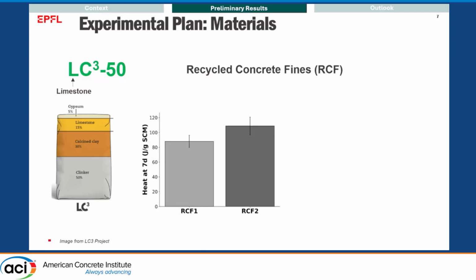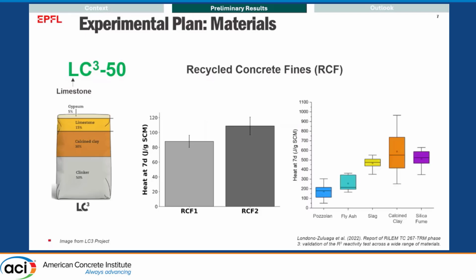So the recycled concrete fines that I was using had an individual R3 heat of almost 100 joule per gram SCM. And to visualize how this performs compared to other SCMs, I would like to bring back this heat envelope graph. If you place the R3 heat of the recycled concrete fines, as you see on the right, it is performing equivalent to the lower end of natural pozzolans. So it is not completely unreactive, but it's not very reactive. It's in between.